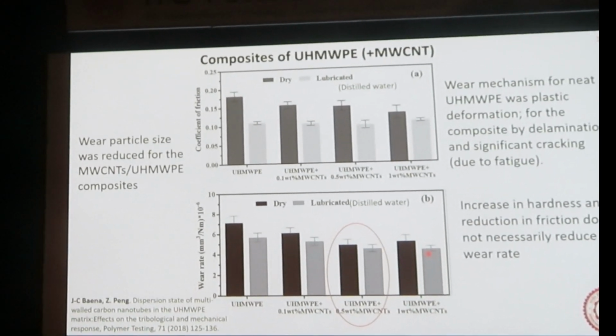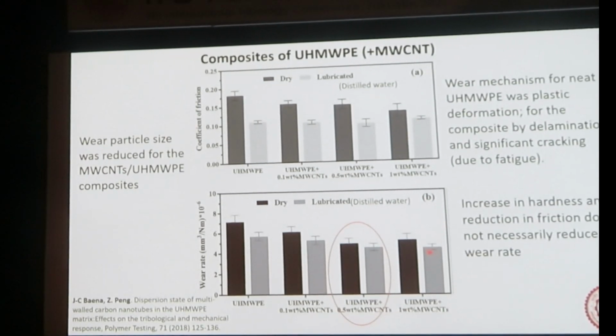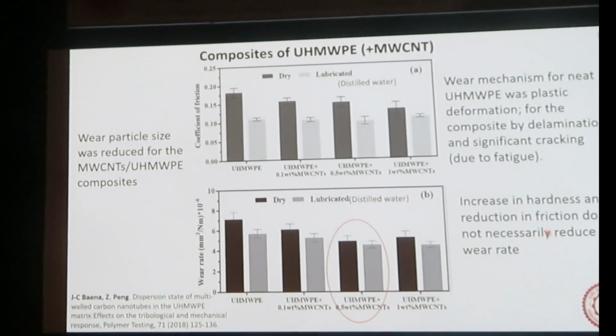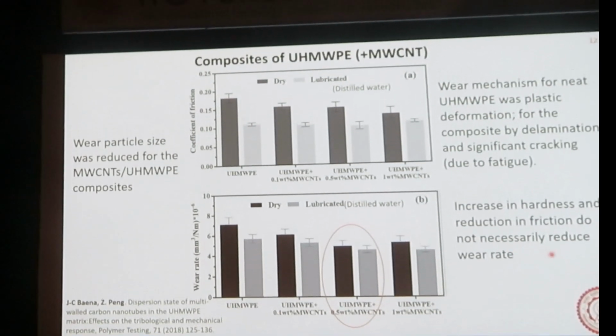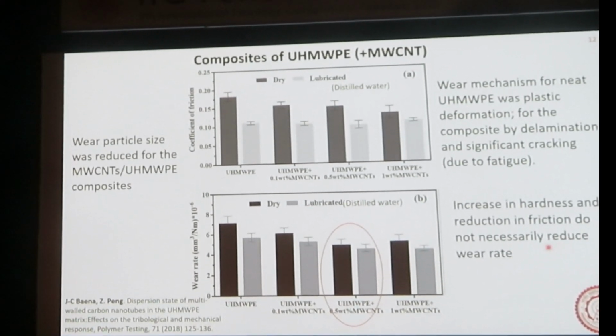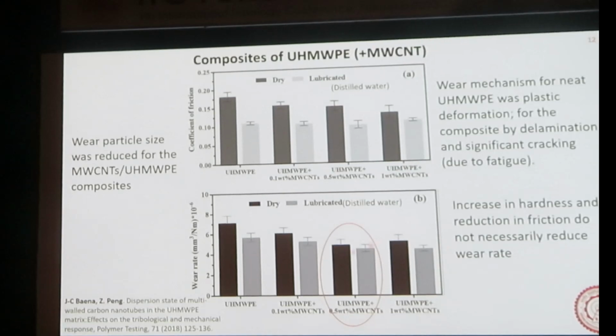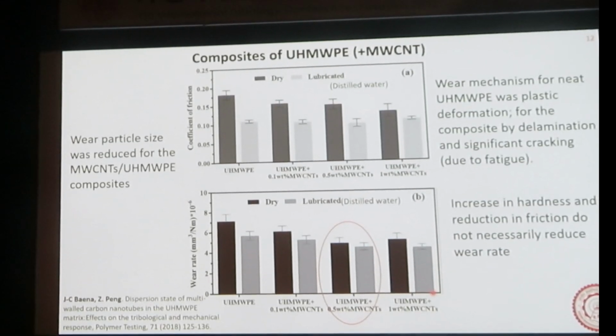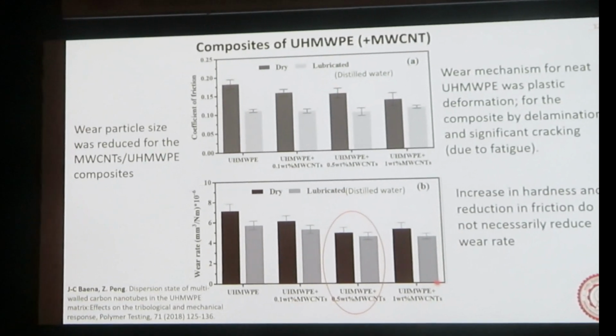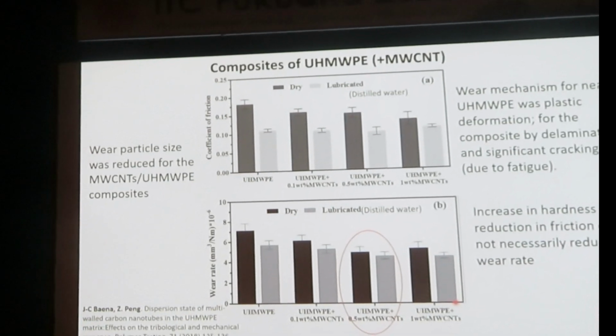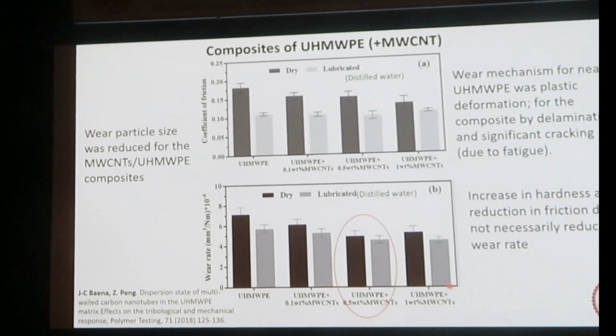for UHMWPE with multi-wall CNT. However, an increase in hardness and a reduction in friction do not necessarily reduce the wear rate, and these kinds of specimens were found to have lots of fatigue issues. So as you make the material stronger, you run into the problem of fatigue. So this is one thing.